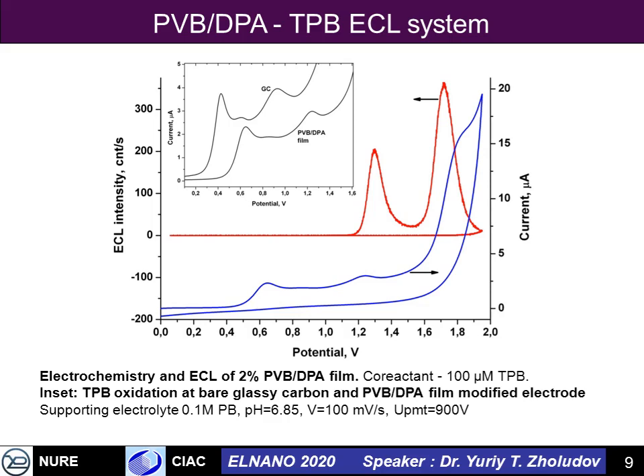During this process, it is clearly seen that the film that is created is semi-permeable. Despite the fact that polyvinyl butyral, PVB, is actually a non-conductive material, the thickness of the film under the conditions used is such that electrochemistry is clearly seen. The current through the film is present, electrochemical current, oxidation of co-reactant is happening, and at potentials of 1.25 volts and also at a high potential of about 1.7, two clearly observable peaks of ECL emission are seen. The red curve is the ECL from such films during the electrochemical process.